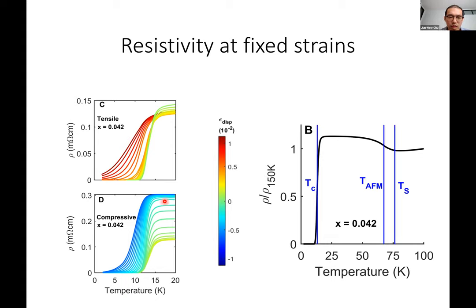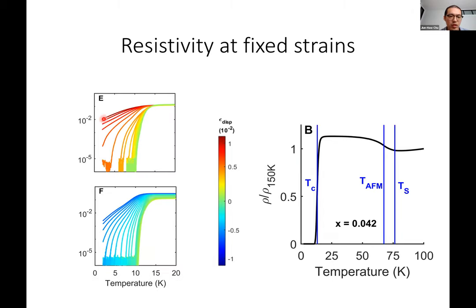But once you fully saturate and fully polarize the domains, and you then further apply strain, you start to actually distort the lattice and push the resistance versus temperature curve towards the left. To make it more obvious, we plot the resistance on a log scale. Then you can really see that the resistance eventually drops into a noise floor at some temperature, but this temperature is being pushed further and further towards zero temperature for either compressive strain or tensile strain.